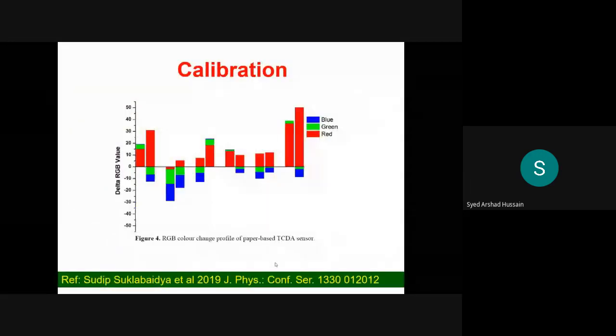And of course, for calibration, you have to take the image of your film, and then take the RGB color combinations from different pixels. And if you analyze with a simple algorithm, then you can have an idea about the concentration also. But work is going on to have a precise idea about the color change with the concentrations.